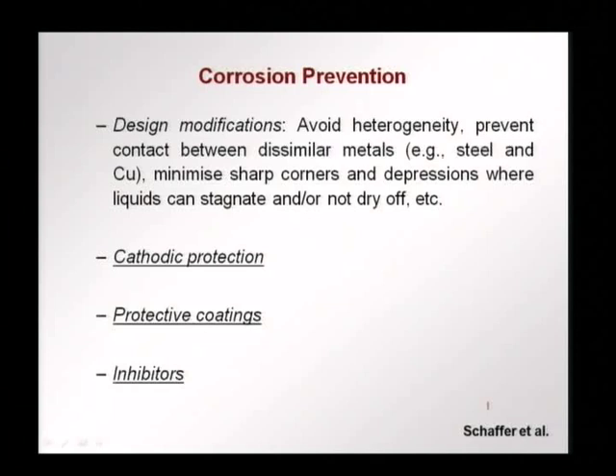We can look at design modifications, avoid heterogeneity, prevent contact between dissimilar metals, for example, steel and copper. So, this again comes from the elimination of galvanic cells between the two dissimilar materials, which will cause corrosion of the more anodic material. For example, if we have steel and copper in contact, steel will corrode. So, this is something that we can keep in mind during design to avoid dissimilar materials from being in contact.